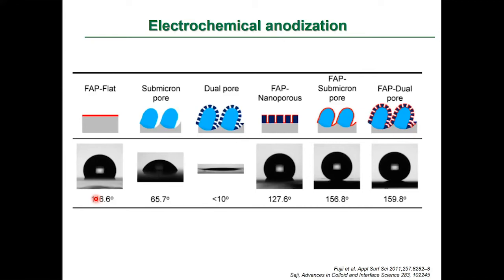Yes, okay, sir. So the contact angle is 116, but with anodization, and the two-step anodization, even though there is a surface roughness, the surface is still hydrophilic, but on low surface energy modification, it can attain the superhydrophobicity.